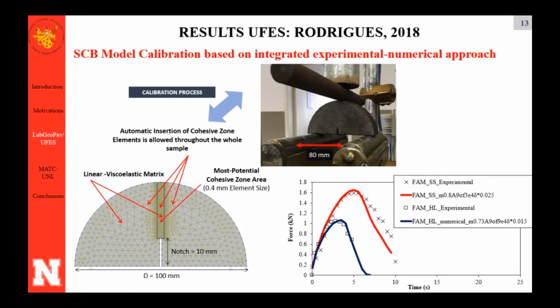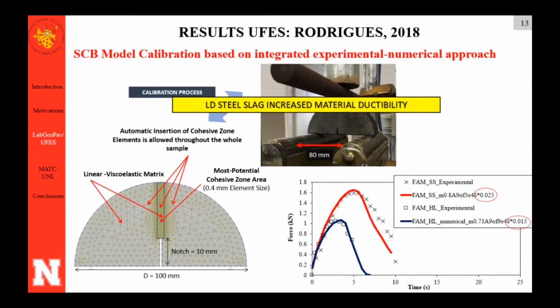There are some changes in the modeling parameters. So this student did a parametric analysis of the effect of each parameter. I'm not going to talk about this parametric analysis, but I'm going to highlight here the change that she observed. For the fine mixture that used slag, the delta value was higher than the delta value for the mixture that used hydrated lime. This, from her parametric analysis, is an indicator that slag may produce a more ductile material.